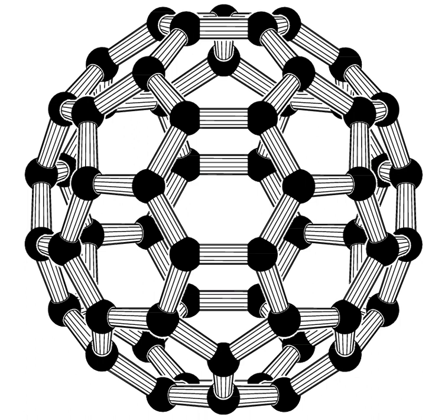Topic: Other morphologies. Carbon nanobuds are a newly created material combining two previously discovered allotropes of carbon, carbon nanotubes and fullerenes. In this new material, fullerene-like buds are covalently bonded to the outer sidewalls of the underlying carbon nanotube. This hybrid material has useful properties of both fullerenes and carbon nanotubes. In particular, they have been found to be exceptionally good field emitters. In composite materials, the attached fullerene molecules may function as molecular anchors, preventing slipping of the nanotubes, thus improving the composite's mechanical properties.